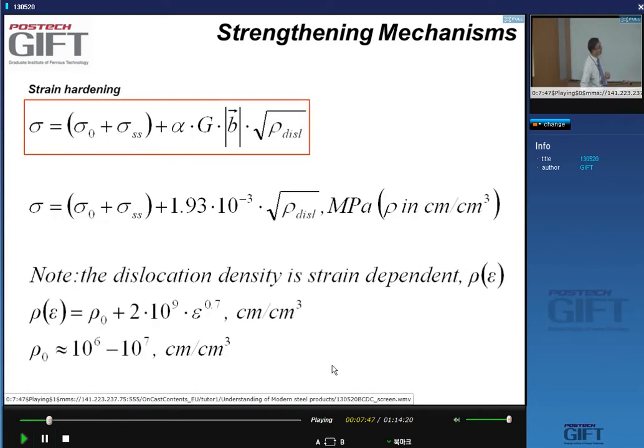And as a consequence, the law for the strain hardening gives me a stress proportional to the square root of the dislocation density. Okay? And this would be like a general equation for the strain hardening. And you can see that you have a lattice strength, a solid solution strengthening factor. And then these factors, alpha, g, and b, are basically constants. But the only variable here is the dislocation density.